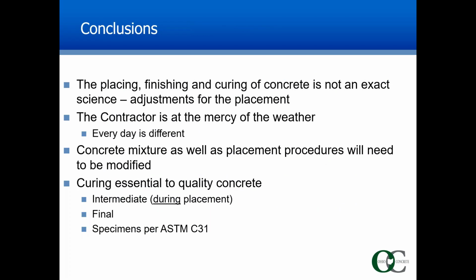So some of the conclusions: placing, finishing, and curing of concrete is not an exact science. There needs to be adjustments for the placement. We understand that the contractor is at the mercy of the weather, and every day is essentially different. Therefore, concrete mixtures as well as the placement procedures will need to be modified for that particular day's placement. Curing is essential to quality concrete. And sometimes we need to apply intermediate curing, which is done with either fog mist or evaporation retardants during the placement, so we don't allow that top surface to dry out. And then placing final curing as soon as possible after all finishing is done. Also, specimens that are cast for job site acceptance need to be placed under the conditions of ASTM C31.